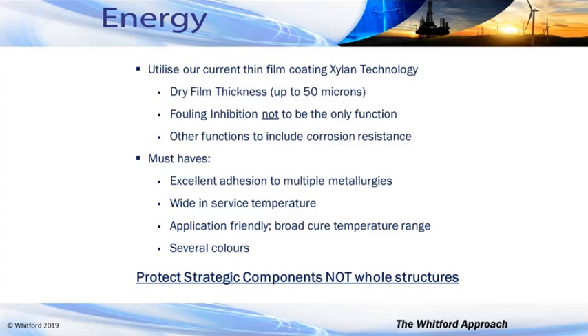It's no use having something which is difficult to apply, because ultimately it's got to be a commercially viable process. And they've got to be able to cure on a broad temperature range. So in terms of our coatings, they are heat cured, they are baked on, and some of these cure temperatures can range up to 220 degrees, and we have to make sure that we can have lower cure temperatures as well in order not to affect the properties of some of the metallurgies where they're annealed, etc.